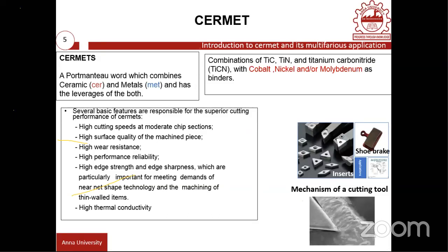The rupture strength of the cutting edge is really good, which should be good for the CERMETS, and we have high thermal conductivity. Compared to ceramics as well as cemented carbide, the CERMETS carries a very high thermal conductivity. As a result, the moment you have heat generation at the chip tool interface, the heat will be immediately taken away from the cutting zone.